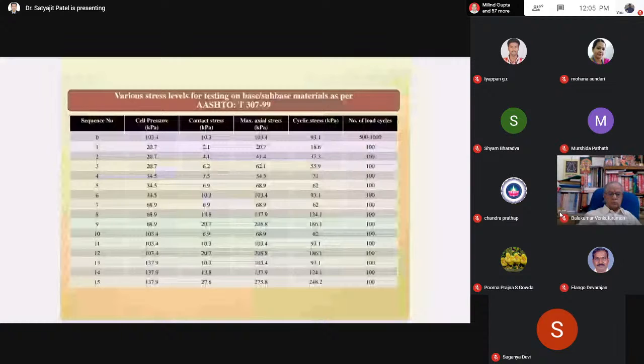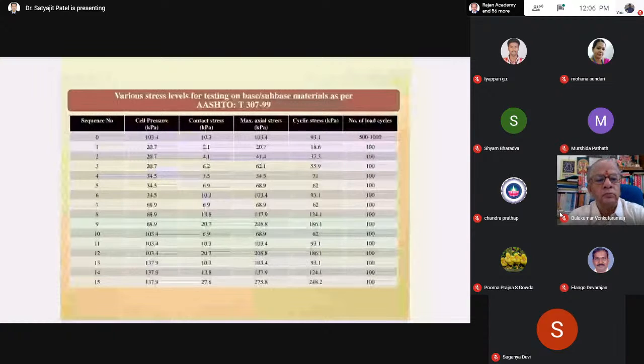If you see this table carefully, there is sequence number 0, and then sequence numbers 1 to 15. At sequence number 0, the cell pressure is 103, then there are contact stress, maximum stress and cyclic stress. Maximum stress minus contact stress is the cyclic deviator stress. These are the stress combinations recommended by AASHTO to be applied for base and subbase material during the resilient modulus test. At these 15 different stress combinations, you will get the resilient modulus value. As the resilient modulus depends upon sigma 3 and sigma d, for different combinations of sigma 3 and sigma d, we find out the resilient modulus value.